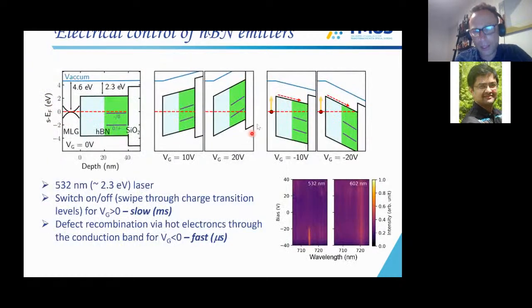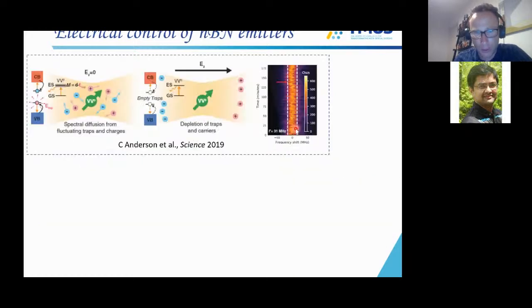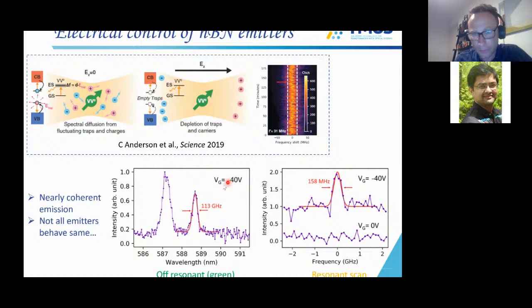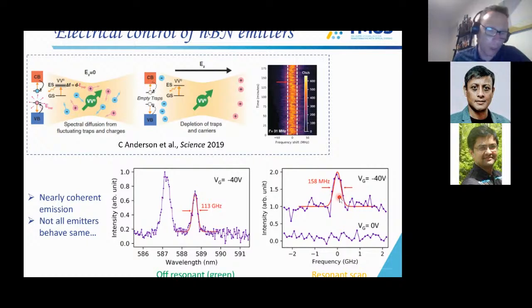So this device under negative bias should do exactly the same, because under negative bias, you should really push all the charges away from the defects and only your defect should recombine. And so we did exactly that. Under minus 40 volts, you can now resolve on resonant. So this is off resonant with the green, you can get very narrow lines, but on resonant, you can actually resolve nearly Fourier transform limited lines. So this is, for now, a very promising way to generate nearly indistinguishable photons in hBN. I should say that we've tried indistinguishable photons, they don't work just yet. There is some decoherence problem, but nevertheless, the lines are becoming very, very narrow.